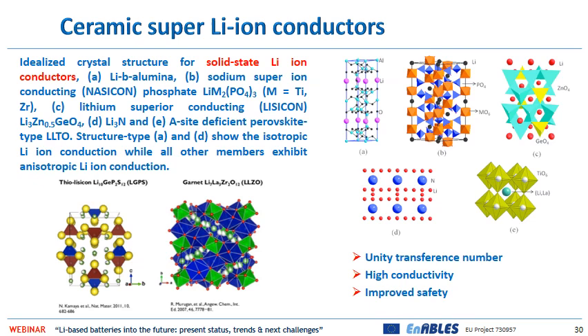Since polymer electrolytes have the softness and flexibility useful in a battery, but their transport properties tend to be inferior to inorganic superionic conductors, the scientific community thought of moving towards the combination of polymer and inorganic materials. This results in hybrid electrolytes which are mechanically stable, with the softness of polymers at the surface of the electrode to enhance the active material utilization and the remarkable ion conduction properties of ceramics. Thus, there is a growing interest in composite electrolytes with inorganic and organic phases in intimate contact.